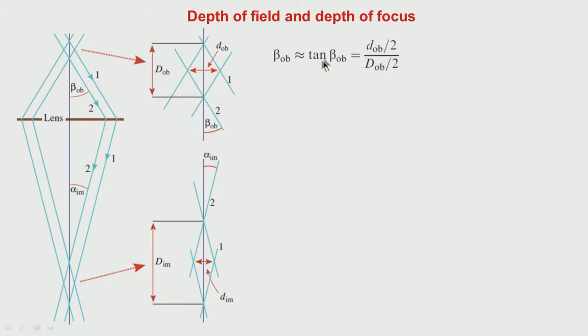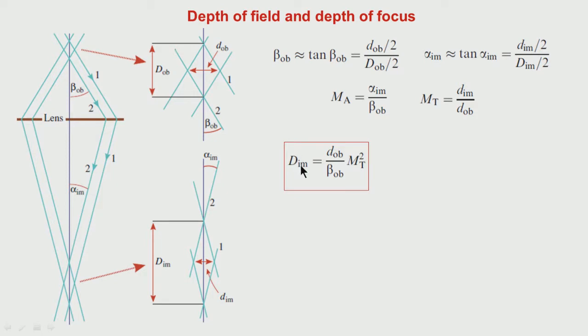So, this angle beta is essentially given by, if you look at this particular diagram, the object size which we wanted to see. Okay. From the ray diagram we can make out that this is the separation for the over focus and under focus condition, within which this much region will be in focus. This we can see for the image plane also. Finally, then we know the magnification of that lens. Okay. Substituting this, we get a formula for D image, that is the depth of focus or the depth of image: the object size divided by the angle which it makes with respect to the lens, and the magnification squared at that time.